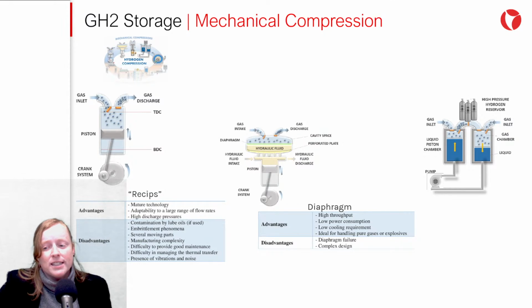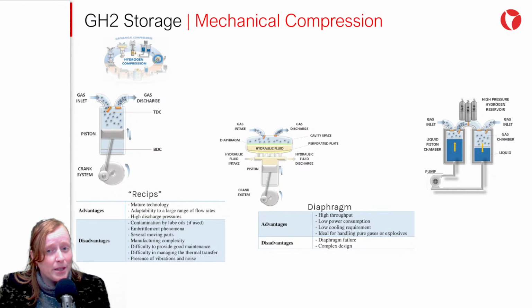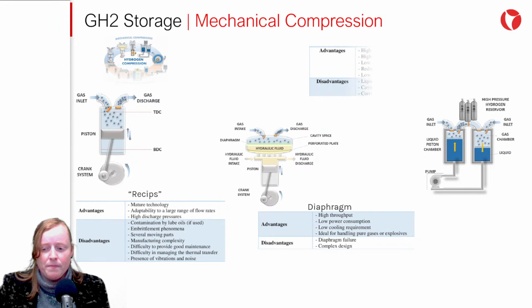Ionic compressors are similar to reciprocating compressors, but use ionic liquids in place of the piston. These compressors do not require bearings and seals, two common sources of failure in reciprocating compressors. An ionic liquid compressor takes advantage of two properties of ionic liquids: their broad temperature range for their liquid phase and the low solubility of some gases, such as hydrogen, in them. This insolubility is exploited by using the body of an ionic liquid to compress hydrogen up to 1,000 bar.